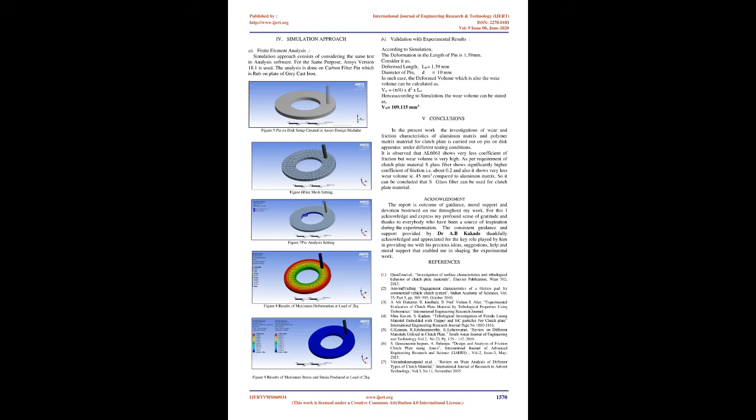3.3 Hardness analysis. The wear system is very important. The presence of corrosion or impact can have a large influence on the relation between hardness and wear resistance. The relation between hardness and wear is actually inversely proportional. The harder the material, the less the wear volume. Hence from the table above, S-glass fiber has the highest hardness amongst all, and so the wear rate of S-glass fiber is less. If aluminum composites are considered, they possess less hardness and hence the wear rate of aluminum composites is high.